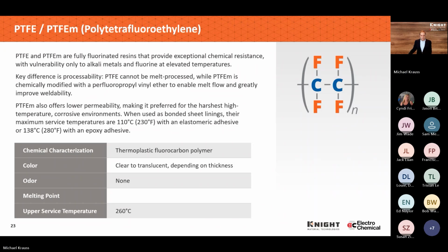those materials. As a general point, for modified PTFE bonded sheet linings, the material cost might be a little bit less, but the workability is challenging. So it's not uncommon that the PFA lining or a modified PTFE lining actually end up really close to each other, because you're trading off. You're adding some challenges with working and using the modified PTFE versus a bit higher material cost with the PFA. But a lot of people tend to think that it's a less expensive total solution because the material costs are lower. And I just want to bring out that it's not necessarily the case.